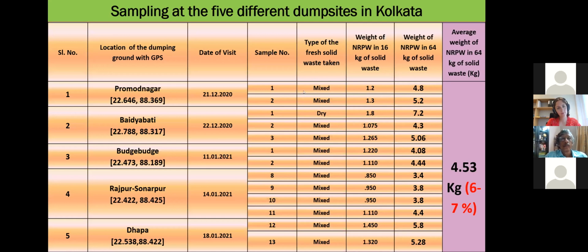And after the collection of the data that we collected from the solid waste and the plastic, we collated the results, in which we found in 64 kg of solid waste, 4.53 kg of plastic waste was found, which is generally 6 to 7%. That is not a very good result actually.